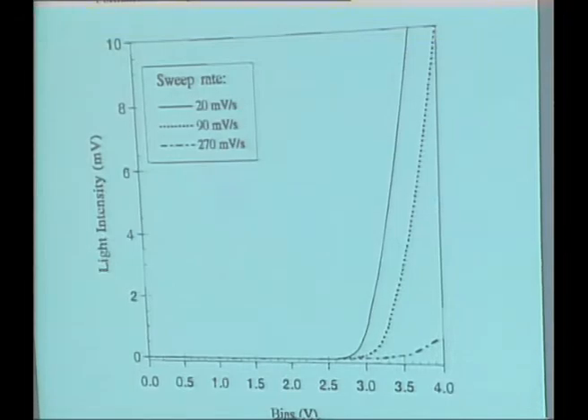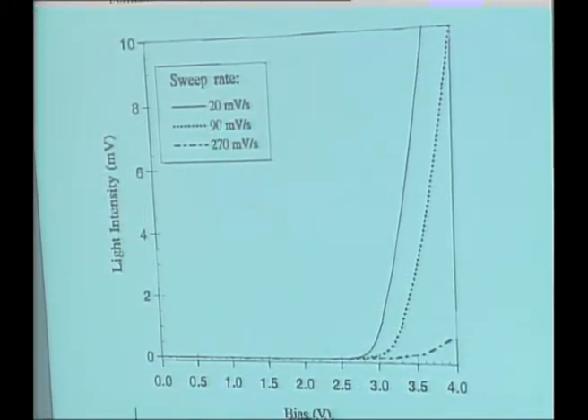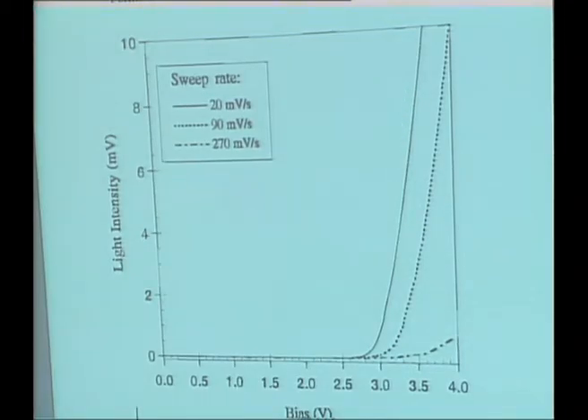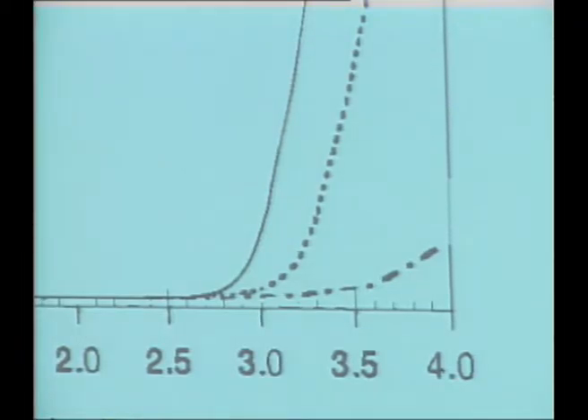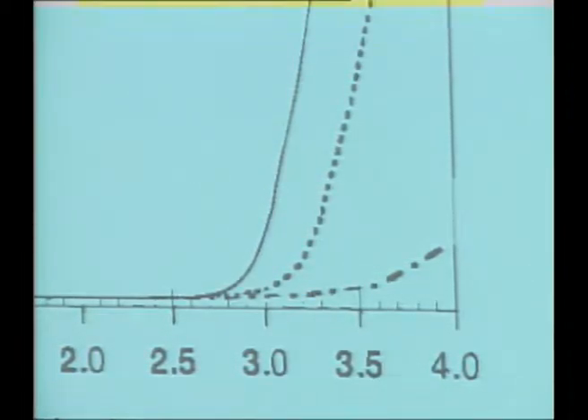But ions have to move here. Ions have to diffuse as you dope the polymer. So you would expect, and indeed you find, that if you sweep the voltage more rapidly, the ionic charge cannot diffuse fast enough, and one does not get this quasi-equilibrium behavior. You're way out of equilibrium here because you're going much too fast. So these data are consistent with ion transport being a limiting feature.